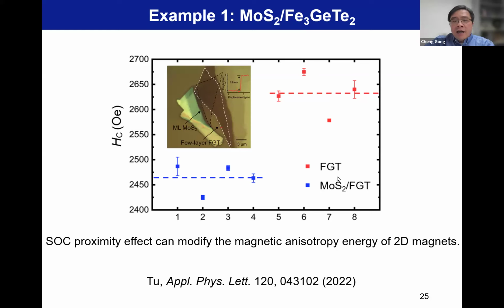So this figure shows that we have 2D iron germanium telluride, it's not that 2D, it's 8 layers. But when you put just one layer of molybdenum disulfide on it, you can see that at 100 K, the coercivity changes by close to 200 oersted. Please keep in mind the coercivity I measure here is from all the 8 layers. So I believe if you could zoom in to just see the interfacial FGT layer, probably the coercivity change could be even larger. But anyhow, you can see just one layer is enough to change the 8 layer sample's coercivity. Coercivity is a direct reflection of magnetic anisotropy. So certainly here, there is a strong interfacial effect.